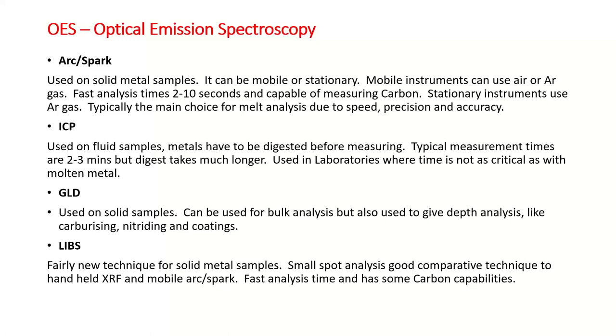Glow discharge, again, for solid samples. It can be used for bulk analysis, but it's also used to give depth analysis. The technique actually sputters its way through a sample, so you can see the coatings as you're working through. So if it's something that's been carburized or it's had nitriding done to it, you can actually see the nitrogen layer or the carbon layer, and you can work deeper into the sample so you can see what depth that's come down to. You can make sure that your heat treatment's been doing the job correctly.